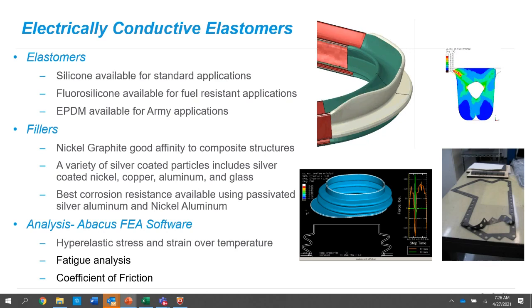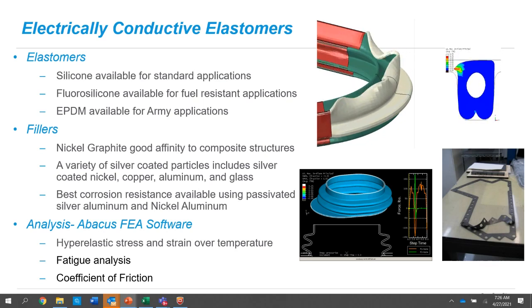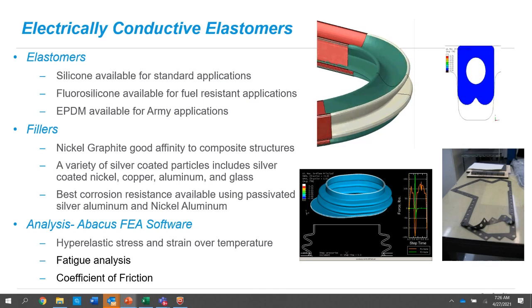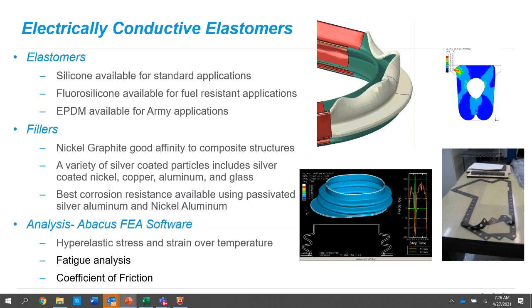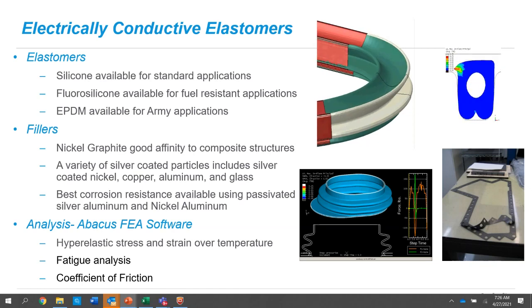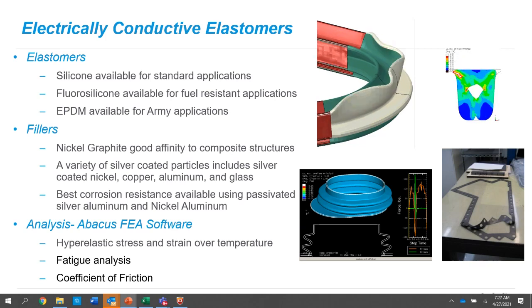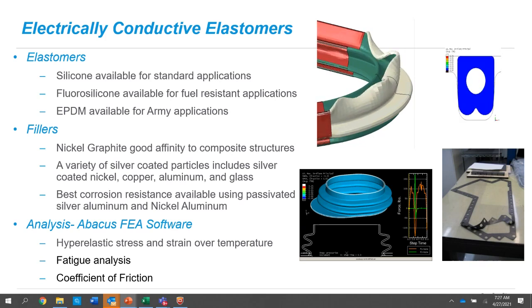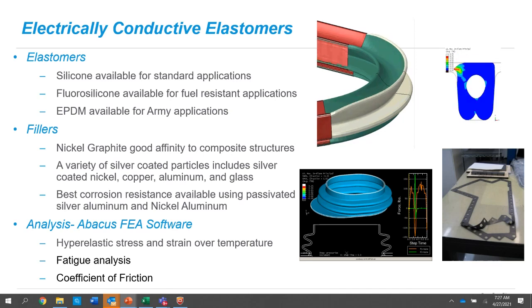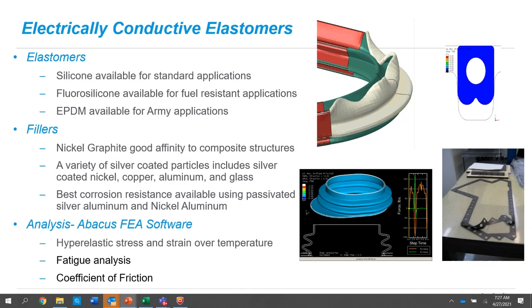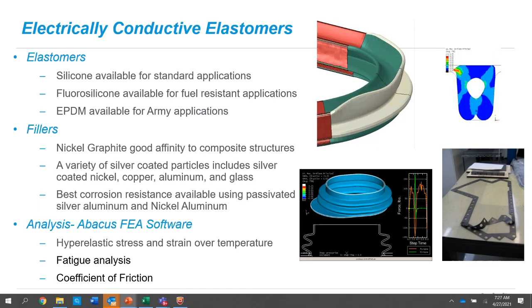So we do a lot of analysis on the mechanical properties, and that upper left-hand corner is a dual blade seal, which was really developed for a very rigorous environment. It sees 10 psi of pressure from the internal and the external, so we needed a dual seal, and then its environment went through every one of those tests I've talked about so far. So we get involved in a lot of rigorous applications, and using this analysis software really helps us to hone in on the best designs.